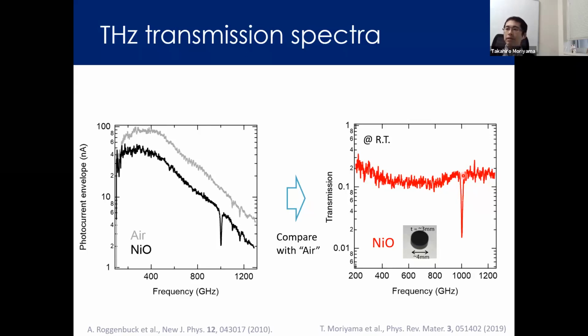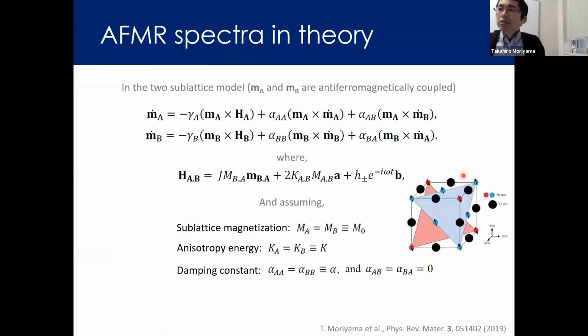So in the next slides, I'd like to show how we analyze the resonant peak. The nickel oxide is basically made of 2 magnetic sublattices. It's a simple collinear antiferromagnet. And these sublattices are coupled antiparallel to each other, something like this. Each sublattice A and B has an equation of motion resembling the so-called LLG equation.